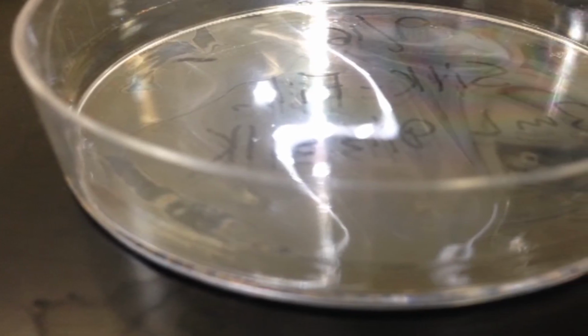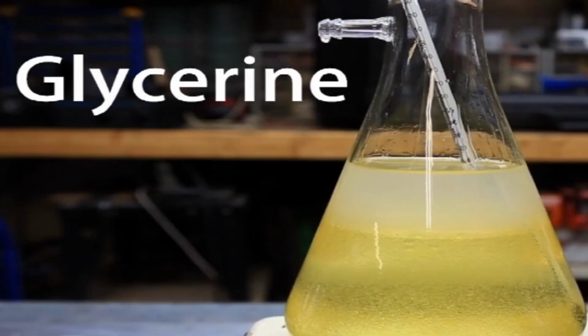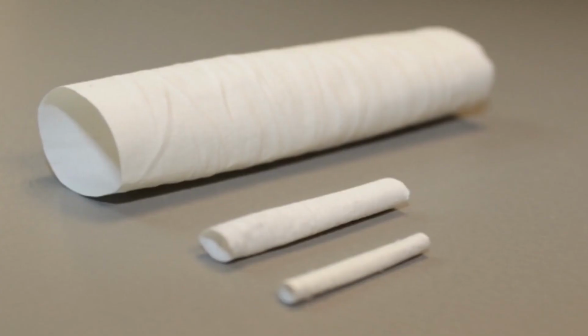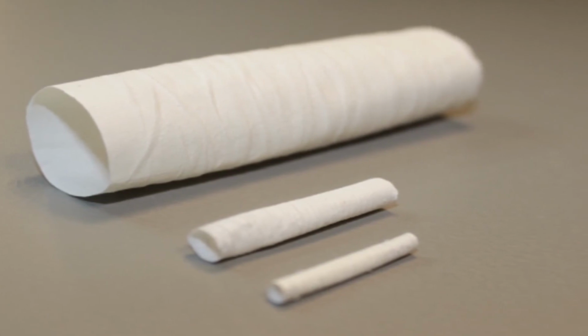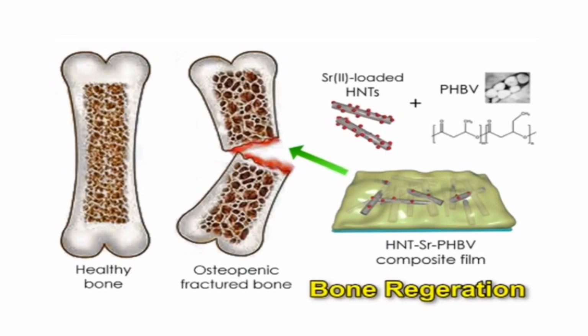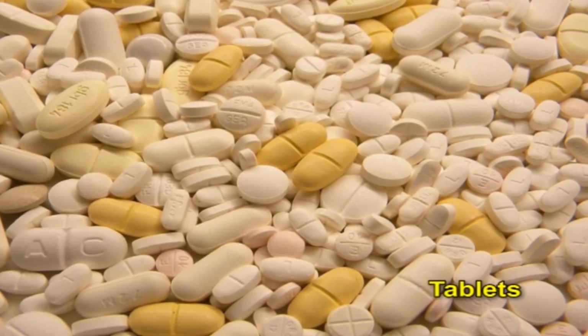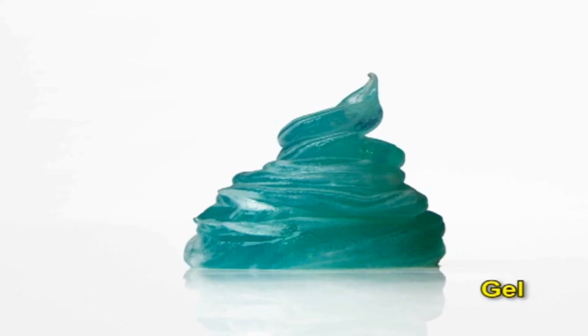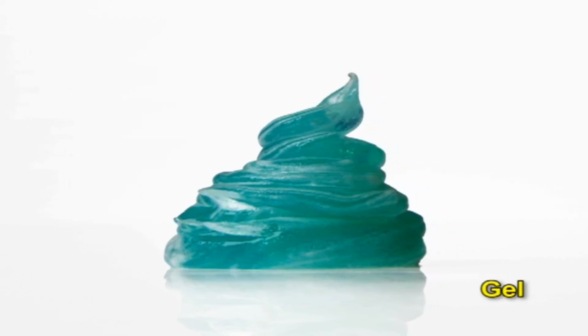The fibroin hydrogels prepared either by treating a 2% silk fibroin aqueous solution at 4° temperature or by adding 30% glycerol could be used as scaffolds able to promote in situ bone regeneration. Using fibroin, controlled release tablets, gels, and microspheres have been prepared.